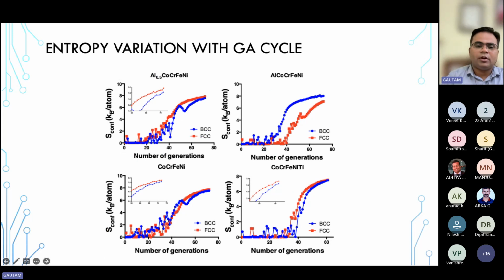So with that, we basically carried out the configurational entropy calculation for 4 alloys. As you can see, in the context of cobalt, chromium, iron, nickel at room temperature, FCC has a higher entropy parameter, and it is stable in FCC form. So what we did, we added aluminium, half of the aluminium. Still, FCC remains stable, which is the case. We're just expanding this data to show you that FCC is a stable phase. And similarly, as we go to equiatomic composition, this flips, and now you have BCC coming out to be the stable phase, which is the experimental data which is available.